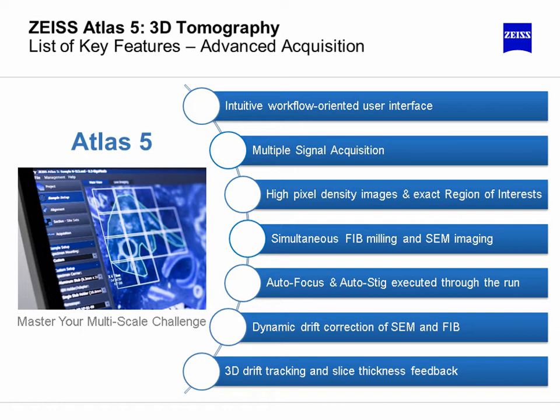Further, the solution exploits the possibility of simultaneously performing SEM imaging while doing the FIB milling. There are autofocus and autostigmation routines that can be executed through the run to maintain the best image quality possible. Further, we have taken care of correcting for any drift of SEM and FIB beams and tracking the thickness of the slices. These are measured live, and there is a feedback mechanism to ensure that the system maintains a constant slice thickness through the whole tomography run.